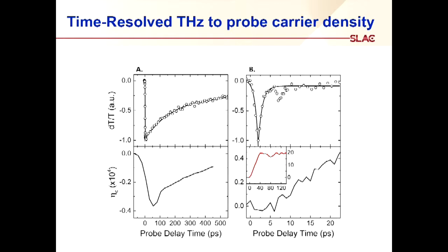And when we correlate this behavior with the X-ray measurements of the strain, we see that you get this compressive strain in moly disulfide on basically a similar period of hundreds of picoseconds. And in the case of rhenium disulfide, you never get much compressive strain. In fact, the time resolution of this particular X-ray measurement was not so high. So if there had been a compressive strain over this brief time interval, we wouldn't really have seen it experimentally. So we had a very strong experimental correlation between the presence of electronic excitation and the compressive strain, the contraction of the crystal lattice.